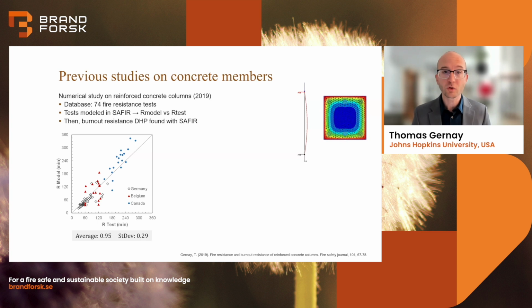In other cases, a same laboratory repeats a fire resistance test on two identical reinforced concrete columns and obtains quite a significant discrepancy. So there is also variability in nature and in the experimental process. All of these are reflected in this dispersion. It's important to recall that whenever we do one test or one model, there is variability, there is uncertainty as well, even though on average we are confident that we are capturing what's happening.